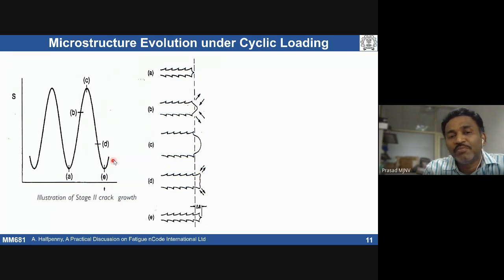But when it comes down to point E, it can become sharp again, because a lot of blunting has taken place. Finally, the front has moved from this location to this location. This much movement has taken place in one cycle. I applied stress from minimum to maximum and maximum to minimum. The crack front has moved due to local plastic deformation, shearing activity, so we see the bulging. Then in the reverse direction, when you drop to the minimum stress, we see some blunting, and we are left with an extended crack. So this is how one cycle can make the crack front move a certain length, depending on how much stress you are applying. That changes how much front extension has taken place.